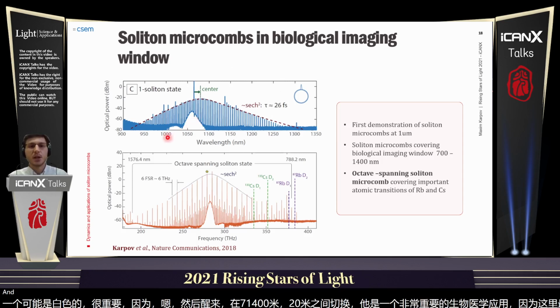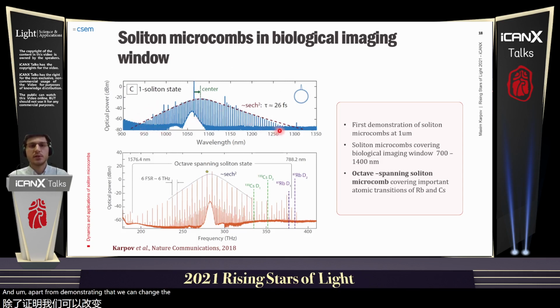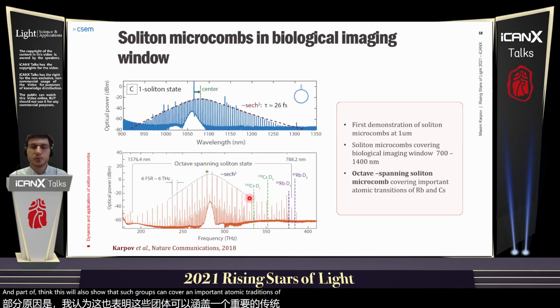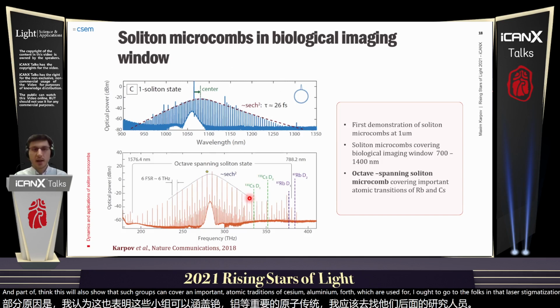And apart from demonstrating that we can generate the solitons in this region, we also demonstrated that we can design devices which enable octave spanning soliton states. Why is it important? Because it can help to self-reference the soliton state, essentially stabilize its repetition rate and offset frequency. And apart from this, we also showed that such combs can cover important atomic transitions of cesium and rubidium, which are used for optical atomic clocks and laser stabilization.